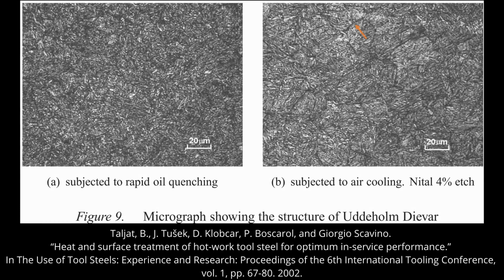In a study on Uddeholm Dievar tool steel, they compared toughness between air cooling and oil quenching, so the oil quenching is much faster. They found the same 48 Rockwell C hardness with both conditions, but the oil quench steel had 25% better toughness. They took micrographs of both conditions, and in the air-cooled condition, you can see the grain boundaries. This is because the carbides were precipitating on the grain boundaries, and then they etch as dark grain boundaries, where the oil-quenched microstructure is even and there's no visible grain boundaries.